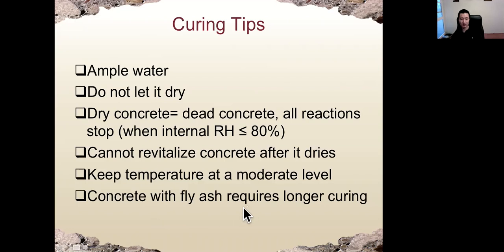Concrete with fly ash or slag, these mineral admixtures, will require longer curing time because when we put fly ash in concrete, we have a pozzolanic reaction. The pozzolanic reaction, discussed in an earlier lecture, is the chemical reaction between silica from fly ash or slag and calcium hydroxide, which is one of the hydration products of C3S and C2S. Together with water, it will generate CSH. So pozzolanic reaction requires longer curing time.